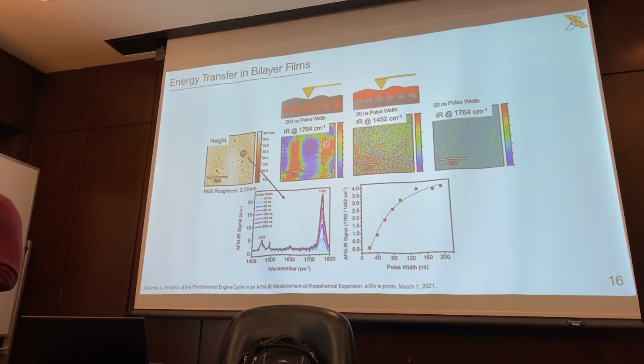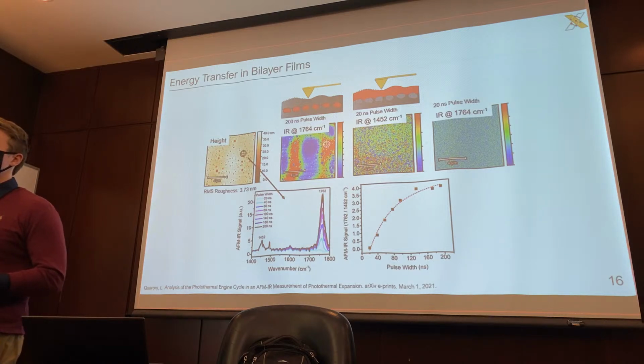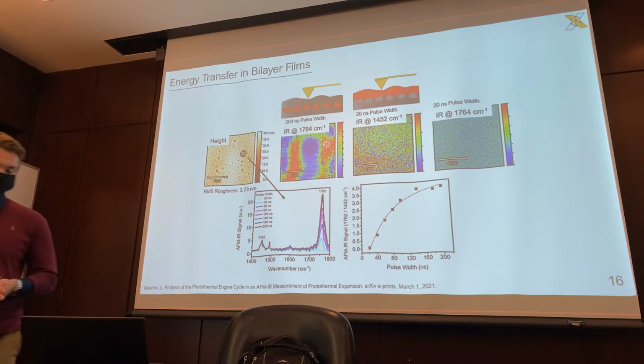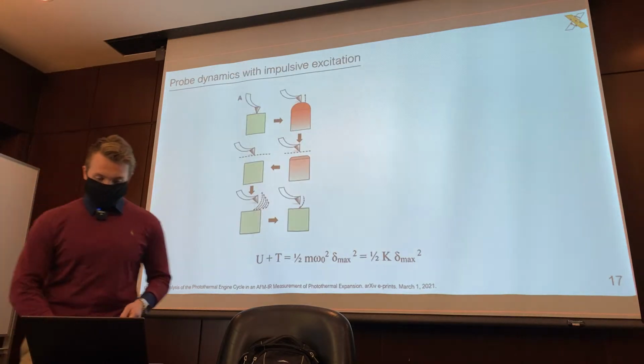Right, and that's why in some of your samples, the best results that I got were when I was using less than 1% laser power, which I never have to go that low. That makes sense then. There's some kind of a localization effect where the heat can't properly expand and then contract. Right.